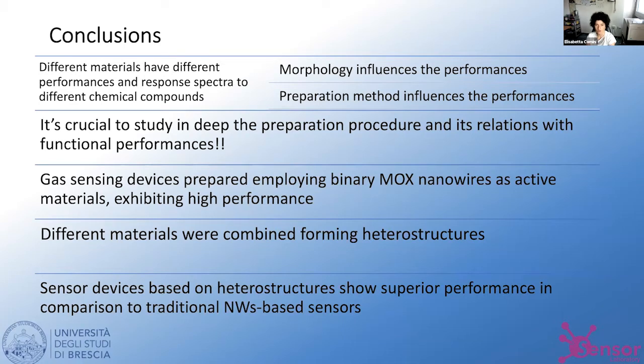This is why it's really crucial to study in depth the preparation procedure and to be able to reproduce the material and the procedure in the same way in order to have the same functional performances, which is a key factor if we would like to have a real device that can be used in real applications. So we have measured the performances of both binary metal oxides and also heterostructures. And we have seen that in the case of the combination of different materials, so with the heterostructures, we have an optimization of the sensing performances, at least in the cases that we were studying.